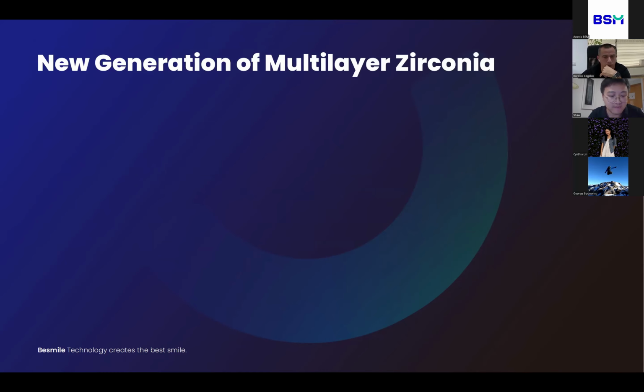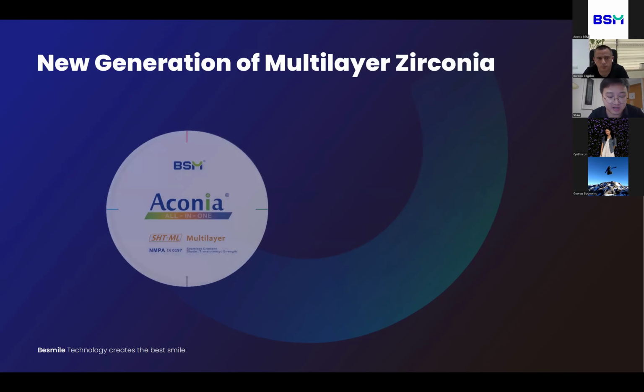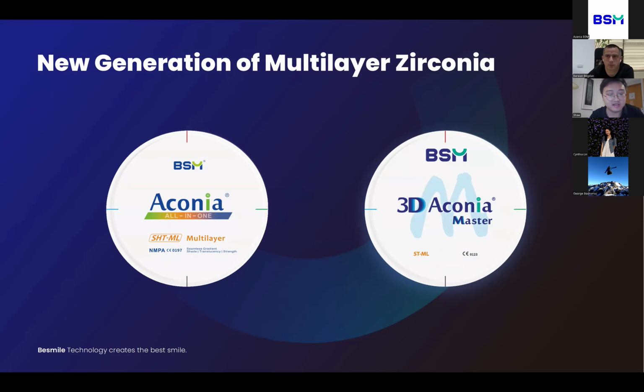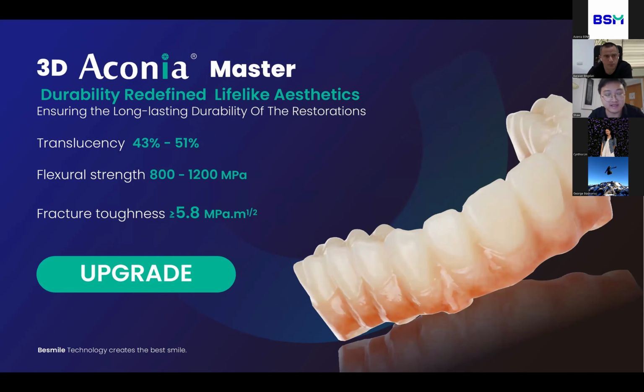As we know, 3D Master is upgraded from the SHT ML, and it is the latest generation multilayer zirconia. We utilize the latest zirconia powder to do the upgrading for better performance. It has the optimal strength and translucency. Translucency is from 43 to 51%. The flexural strength is from 800 to 1200 megapascals. And the fracture toughness is more than 5.8, which can ensure the long-lasting durability of the restorations.